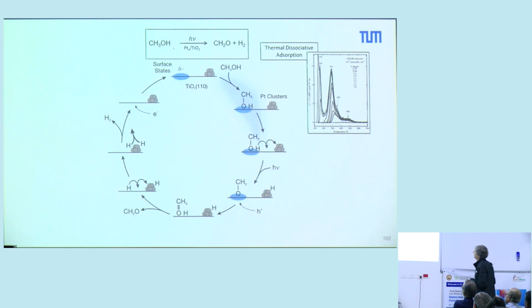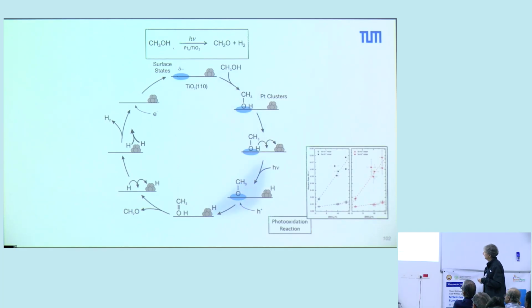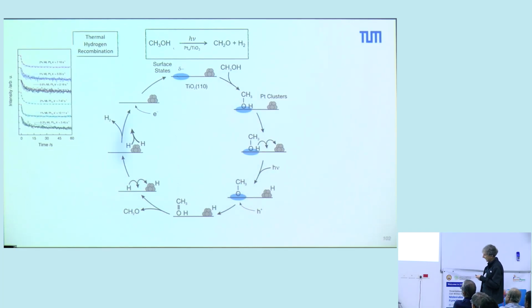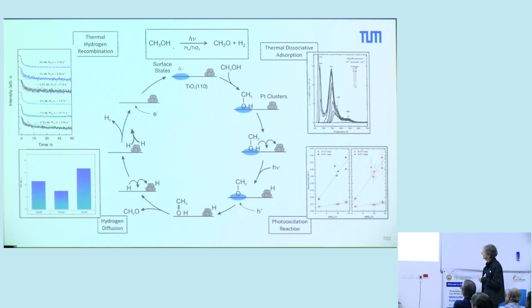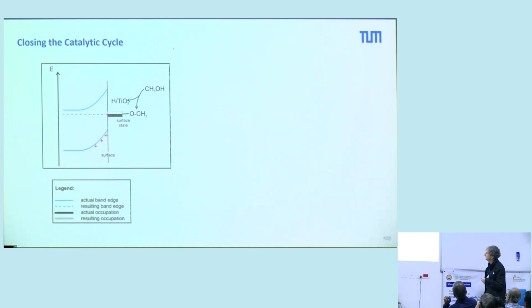I hope I could convince you by different experiments that we have this catalytic cycle of this photoreaction. That means we have the dissociative adsorption of the methanol on this TiO2 site. We have a photo-driven process, the formation of aldehyde. Then we have the migration of hydrogen to the platinum clusters. This is a thermal effect. And then we have the desorption of this hydrogen. So it is a very defined mechanism.